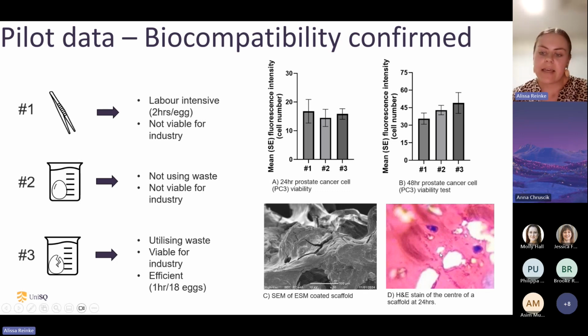And this is a section, so some very preliminary imaging of the scaffold. It was sliced into fine sections, and this image is from the center of the scaffold. You can see that after 24 hours, there are already cells that had made their way to the center of the scaffold, which gives an indication that it's not cytotoxic and the pore sizes are large enough that the cells are able to get to the middle. Therefore, once it grows for longer, we can do more imaging tests to confirm that the cells are proliferating as we would expect.